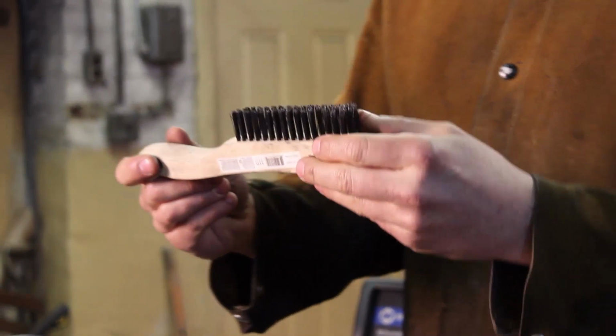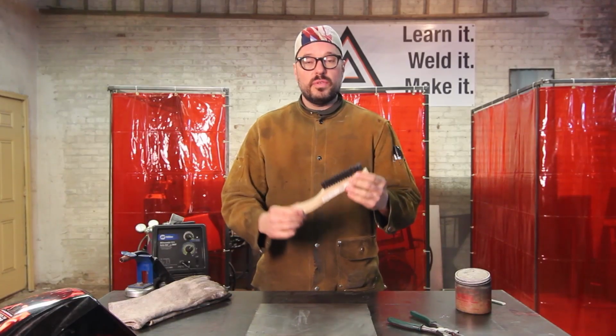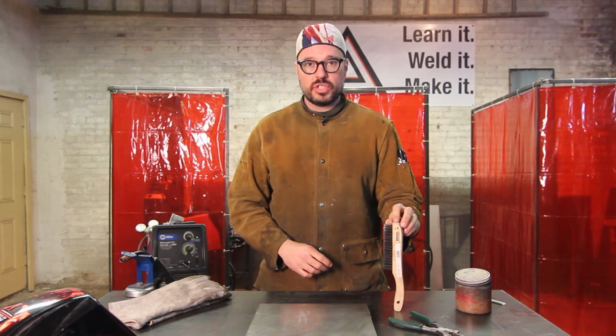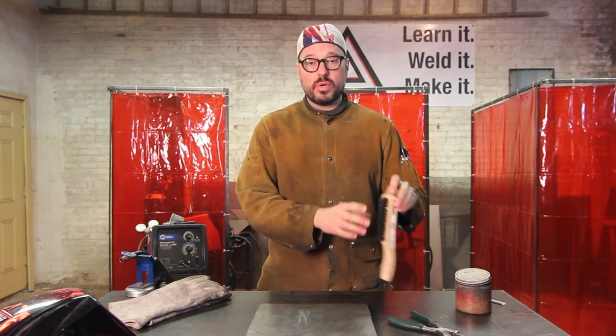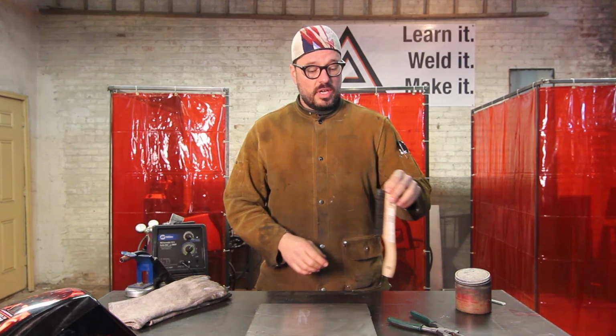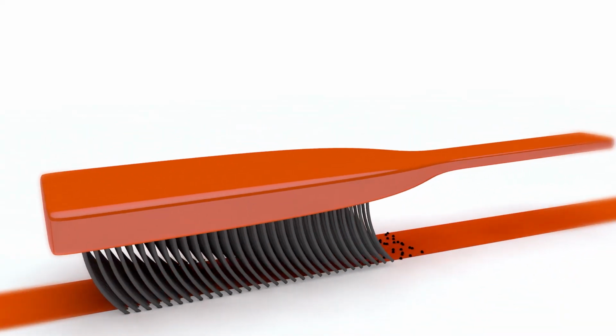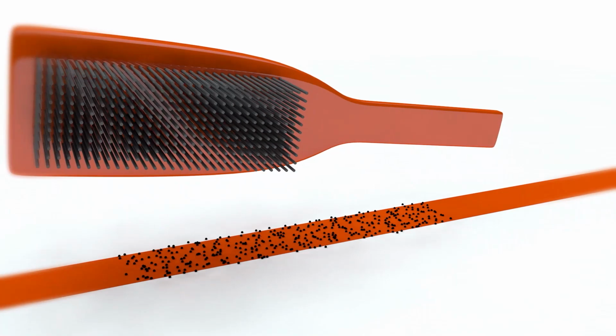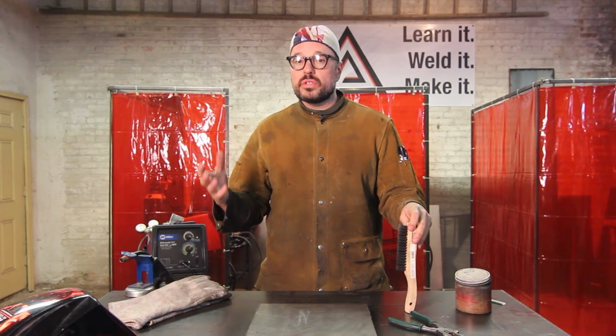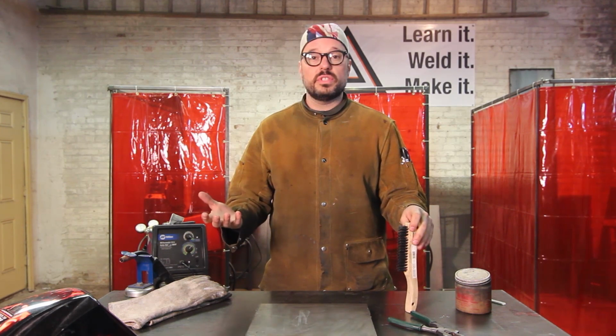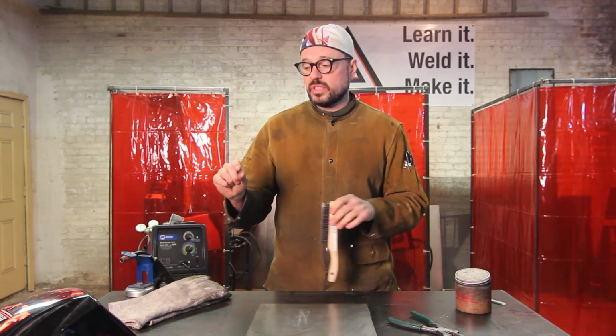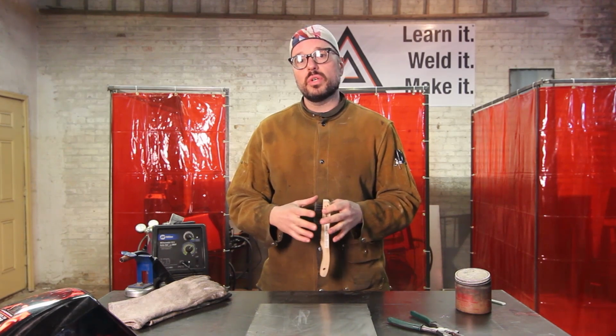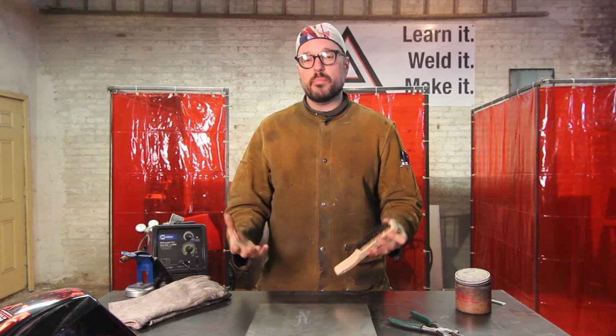Now here's the thing, I said for all of your metal products, if you take a carbon steel brush and then you use that brush for aluminum, you're going to contaminate your aluminum weld zone. You're going to have little particulates of steel dust in there. Steel melts around 2400 degrees. Aluminum melts around 1200 to 1400 degrees. Guess what's going to happen? Those little steel particulates are just going to hunker down in your weld zone, and they're not going to go anywhere. They're just going to create a big pocket, and you're going to have a bad day. So stainless steel, keep them all separate. All right, and that is your brush. Now, moving along.